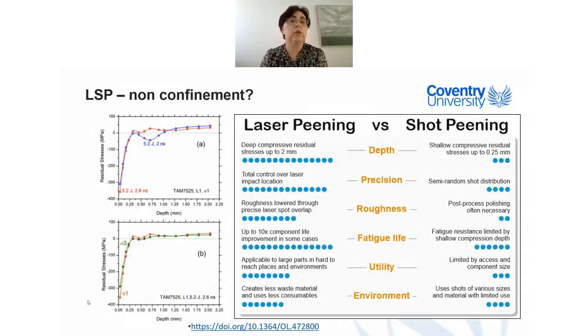I'm first going to point you to an article which was published already in 1995. In this article, you can see that for a pressure of a gigapascal, you need a laser power density in the region of gigawatt per square centimeter. Here, first, I want to show you something down on this graph. If we don't have confinement media, as I said, we can put some pressure inside the material. But with confinement media, we're increasing pressure up to 5 times. And in addition, we're increasing the duration of the pressure wave.